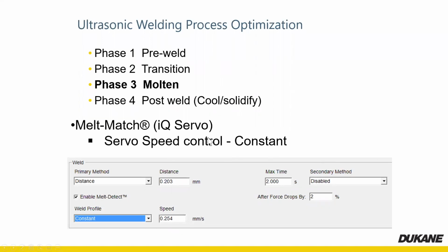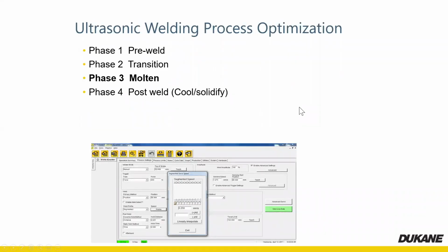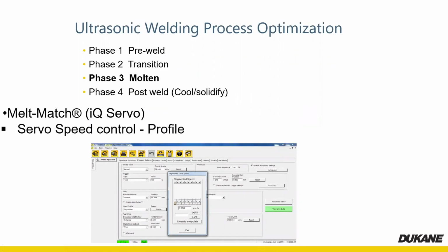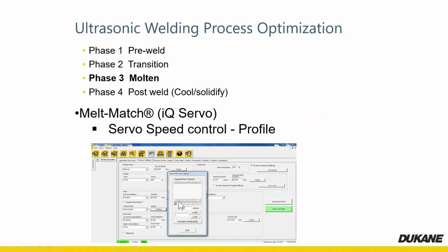Again, this is a constant servo speed control. Now, when we go into a profiled speed control, like is shown here, we actually can adjust these, and here are the 10 segments. So we can start off at 0.25 millimeters per second and increase that as needed. So we've got this molten plastic, and we go faster. We can go slower. We can do a parabolic speed profile, again, depending on the application and what the benefits are. So I've got a few slides here that show the benefits.